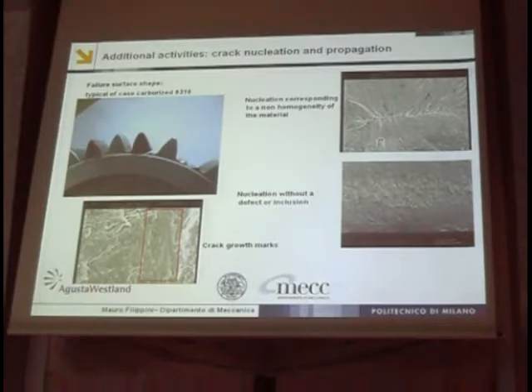So we knew that the failure started from the surface, but we could not detect, on the entire width of the gear, the starting position of the failure. Here, of course, you can see crack growth marks, but this is already in a region where you have high plasticity and fast propagation. This is not a region in the case hardened layer. We were also not able to observe any failures starting at the interface between the case hardened layer and the hardened core. So no failures due to cracking of the interface between the hardened layer and the inside of the material.